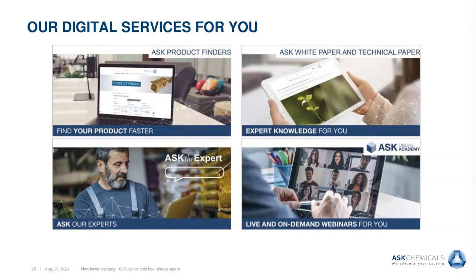Typically, the go-to release agent for no-bake contains aluminum, which is a leafing compound that acts as a release. Ours is called Zip Slip LP78 1495, if you're familiar with it. It's a heptane-based release agent, and it works really well in no-bake. However, if you have an application where you're having a difficult time releasing the core or the mold, you can use 184H or 184H NM2 or really any of the 100% active release agents, and it works really well if you're having issues, particularly on the vertical walls. But the go-to release agent is the aluminum-based heptane containing one. I would only use the 100% active for situations where you're having a really hard time getting the material to release.